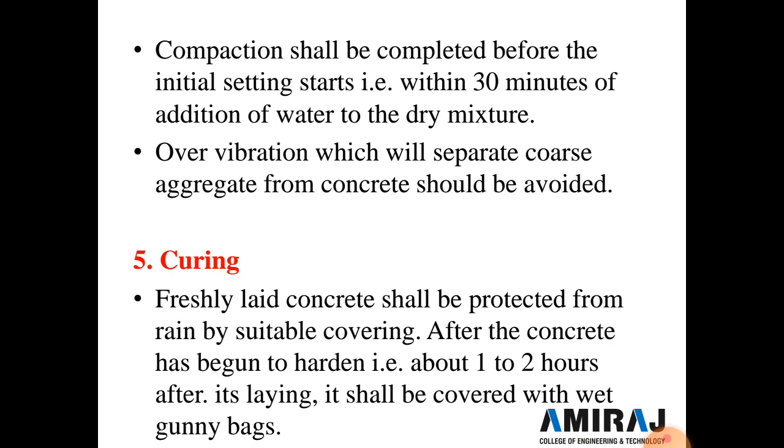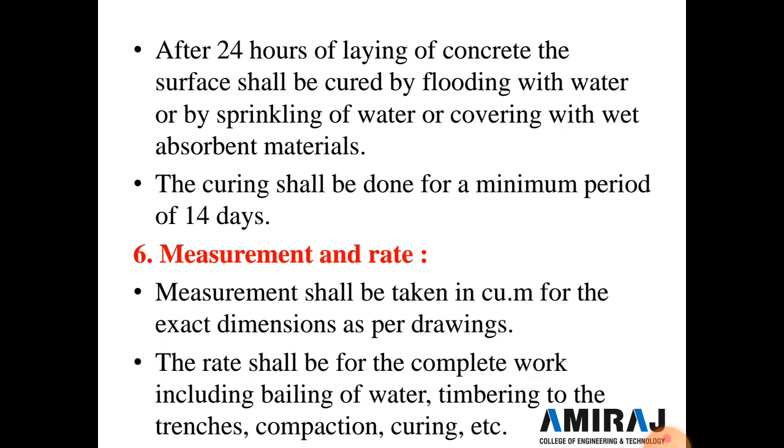And the next point is curing. So here freshly laid concrete shall be protected from the rain by suitable covering. Generally we use plastic sheets, and after the concrete has hardened, about 1 to 2 hours after its laying, it should be covered with wet gunny bags. And after 24 hours of laying the concrete, the surface shall be cured by flooding with water or by sprinkling water or covering with absorbent material, and the curing shall be done for a minimum period of 14 days.